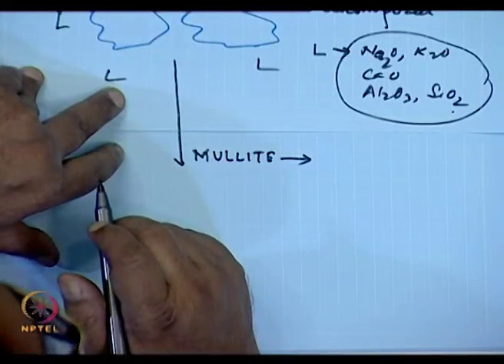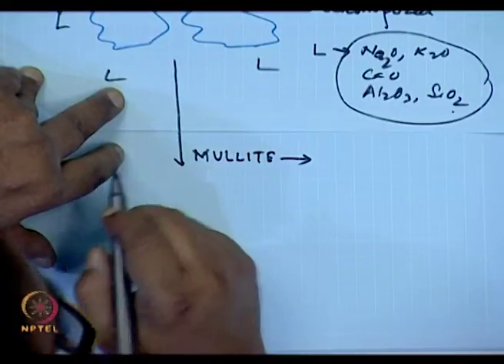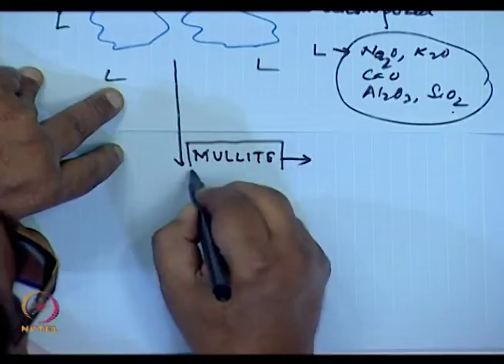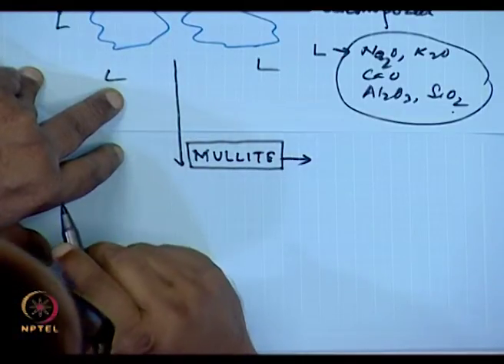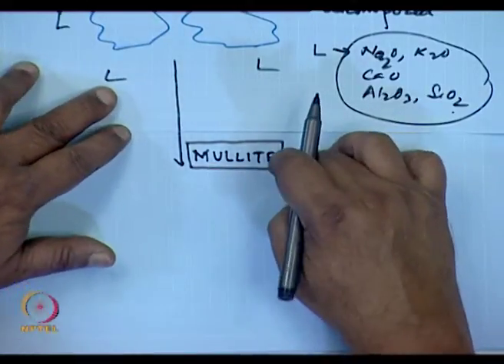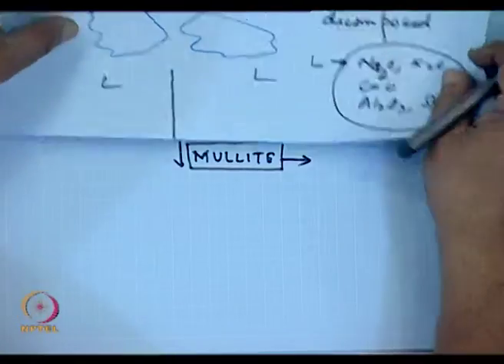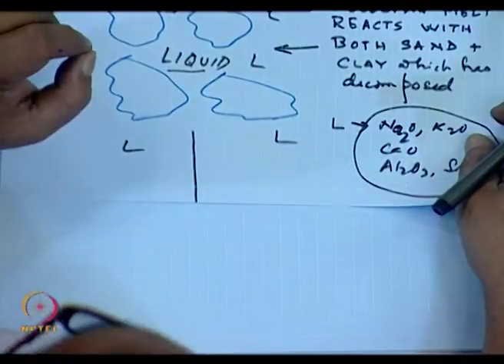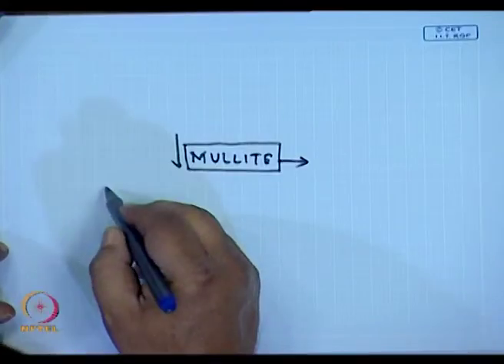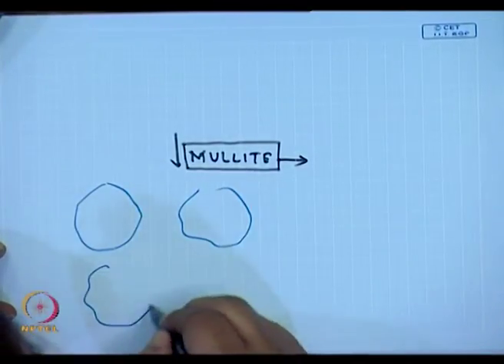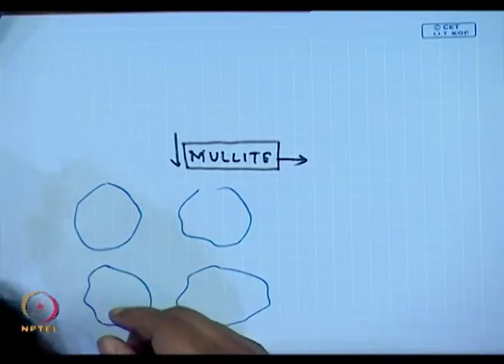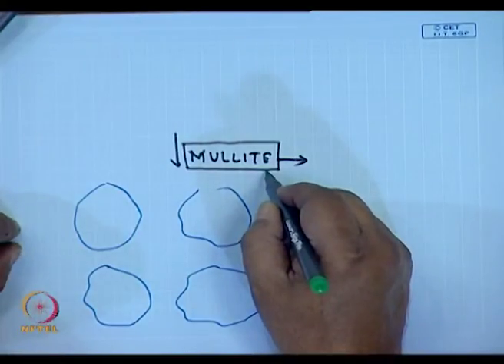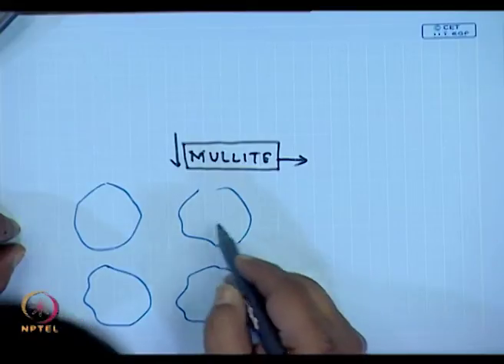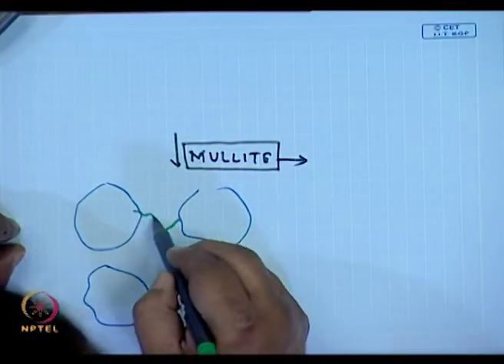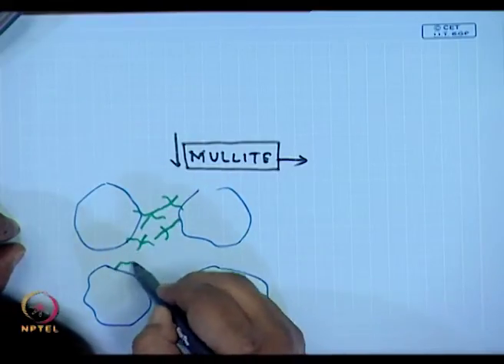I could have given you the composition of the mullite right now, but mullite is a fascinating thing. So I would urge you to Google mullite and find out what it is. Now, at this particular stage, where this liquid has become supersaturated with a lot of alumina and silica, what happens is this: the mullite separates out, and mullite needles start growing out. They start precipitating out.